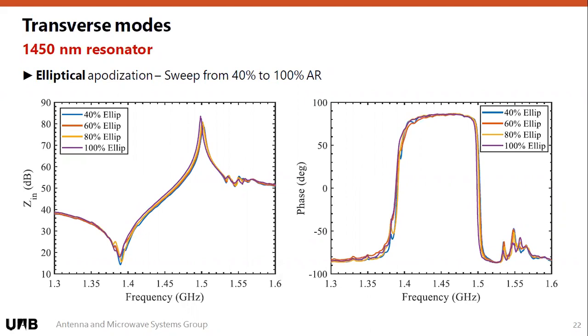So we see that we have cleaned in terms of impedance. You can see that there are no ripples in the middle as we saw before. But see that the cleanliness of the resonator is not as good as the one before. So the fact that you have now an elliptical shape means the apodization grows really fast from the point at which you started doing it. And then you have a really big zone in the middle that is actually completely parallel, so in which you have no effective apodization.